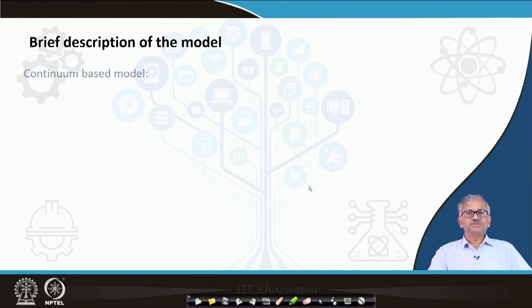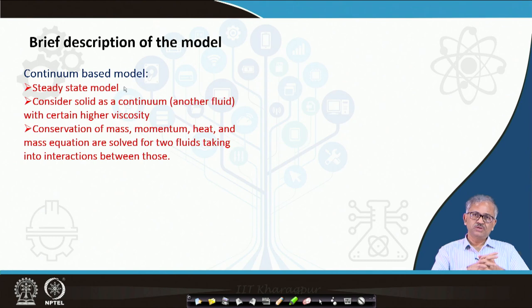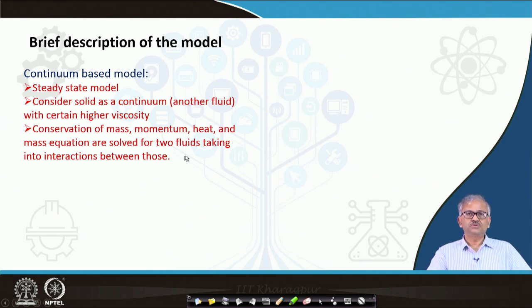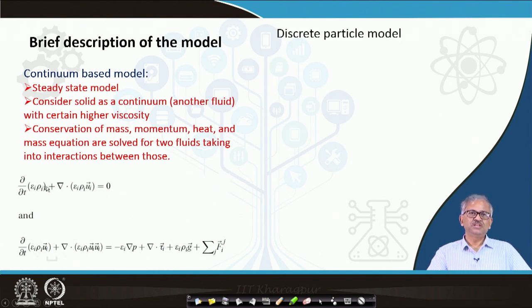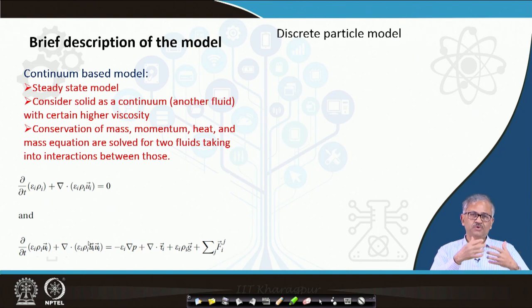For the continuum based model, it is a steady state model considering solid as a continuum fluid with higher viscosity. Conservation of mass, momentum, heat, and mass (species balance) equations are solved for two fluids, taking into account interaction between them. The continuity equation and three-component momentum equation are solved, along with enthalpy balance and species balance equations, and if turbulence is relevant, a turbulence model is also included.